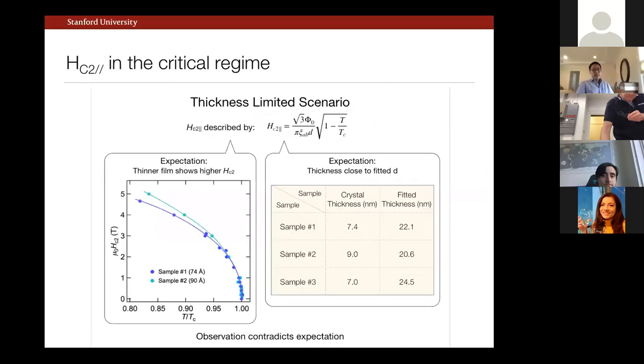Okay, so let's first look at HC2 parallel. So this is putting the magnetic field in the plane of the film and in the critical regime near TC. And what I'm showing you here has a very nice square root of reduced temperature dependence. Jean-Marc, Andrea, many of you that I was chatting with at the beginning, at least in my limited experience, you see this, you say, I know what this is. This is a thickness limited superconductor, as you see in LAOSTO, or in our lab, we've also been playing with geometrically confined delta doped STO.